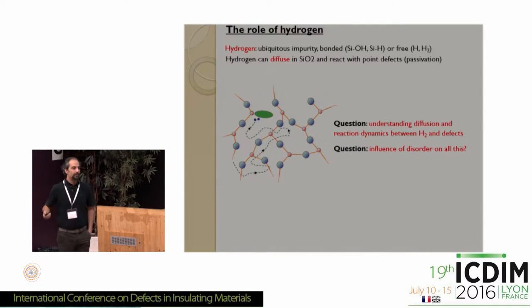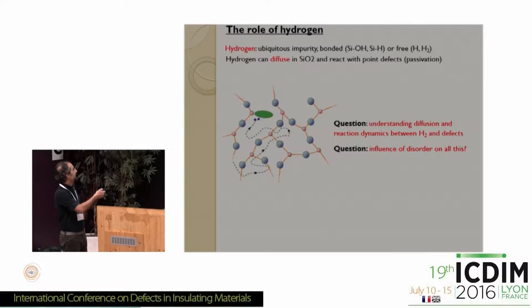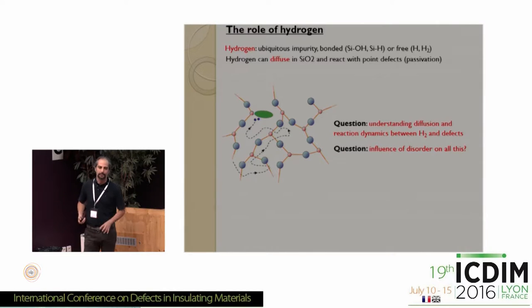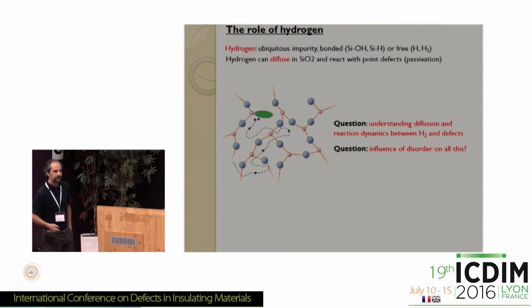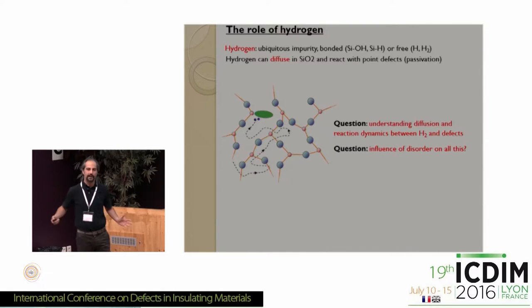So hydrogen is everywhere, an impurity which is present in any material. And in the case of SiO2, but not only SiO2, it can either be in a bound form, so you can find hydrogen in SiO2 in SiOH or SiH groups, but it can also be found in free form. So in a given SiO2 sample, you will usually have a certain amount of H atoms or H2 molecules. And these can diffuse in SiO2. The diffusion constant of H2 in silica is rather large, so at room temperature you have diffusion and diffusion-related effects.